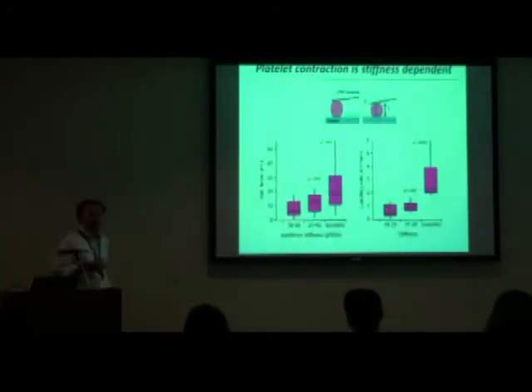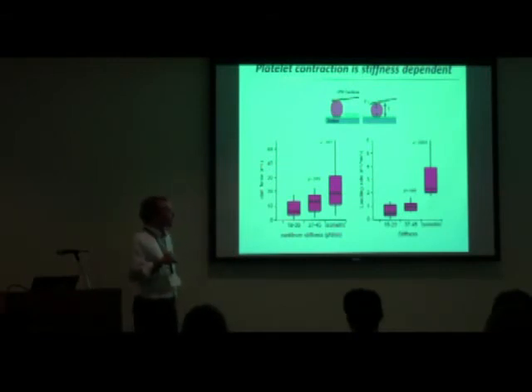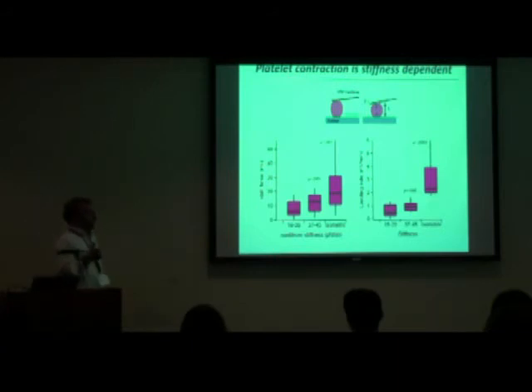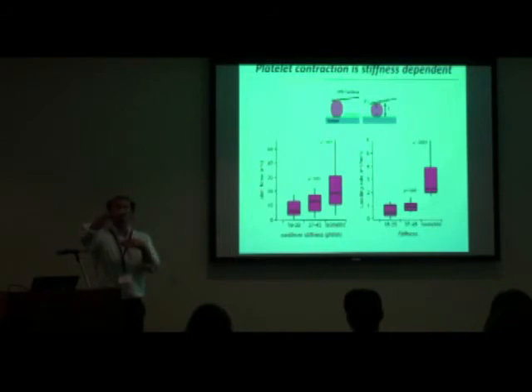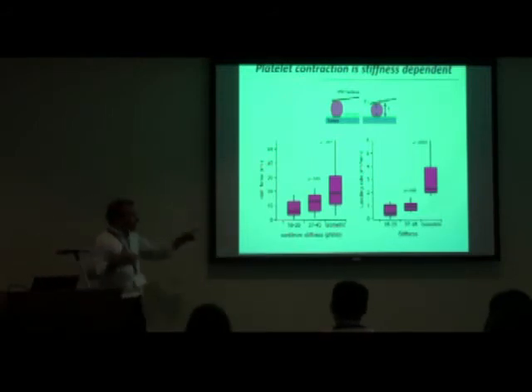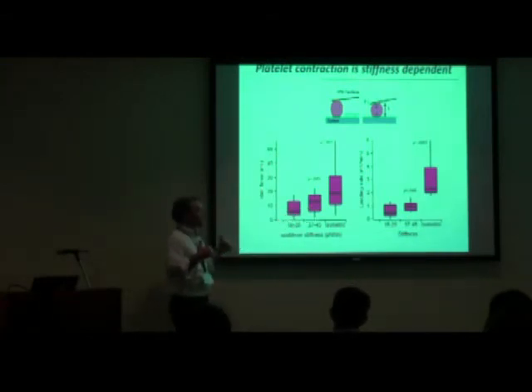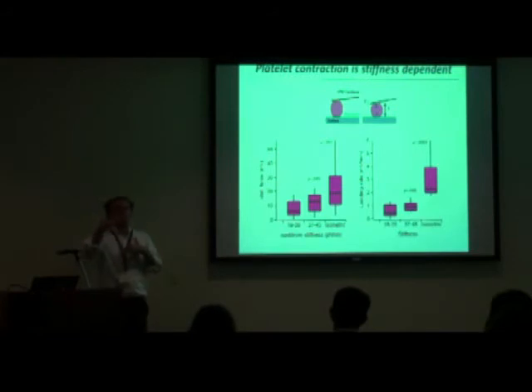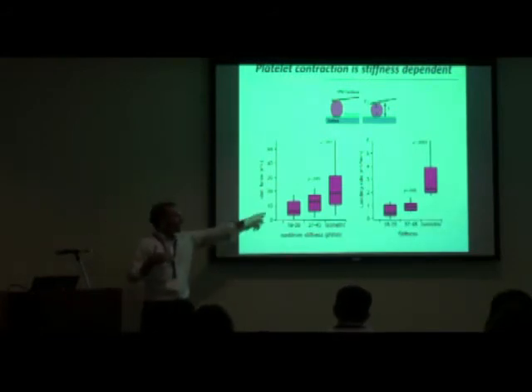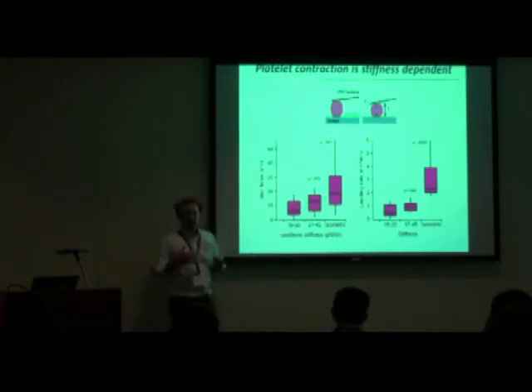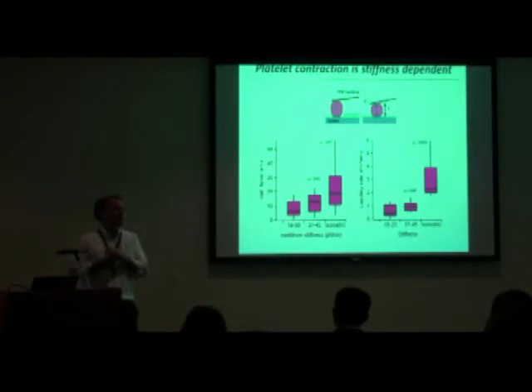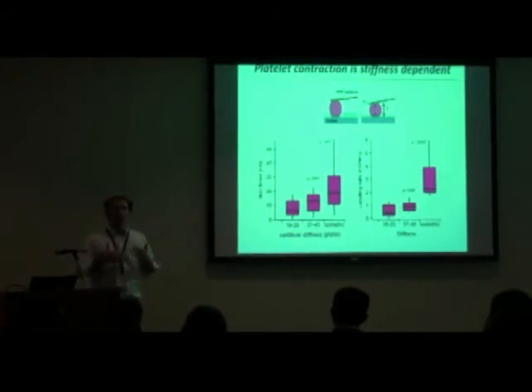Now to the question of the microenvironment. Is the stiffness really an important factor? What we found was that if we change the stiffness of the cantilever, that is, we use different stiffness cantilevers, or if we do a case in which we feedback such that the separation between the cantilever and the surface can't change, the stall force and also the loading rate, the rate at which the force increases, changes. But what that says is that the platelet machinery is sensitive to the stiffness of the clot, and in fact is able to pull harder on a stiffer clot. Now why might we want it to do that? What would be a good thing about pulling harder on a stiffer clot?